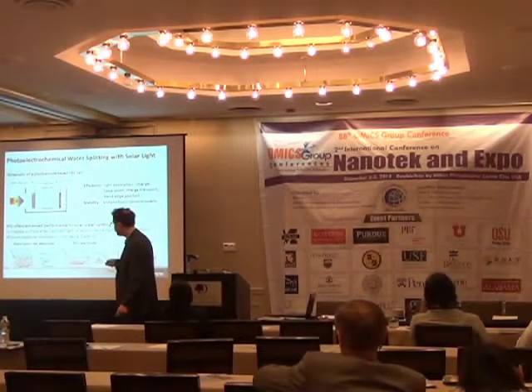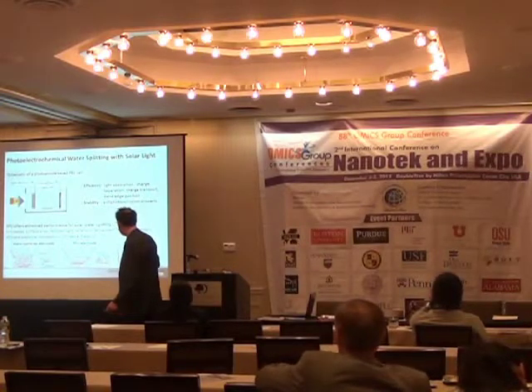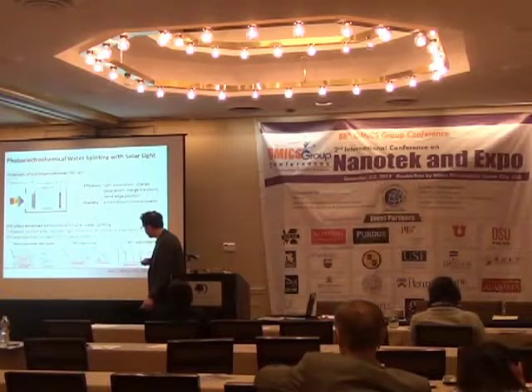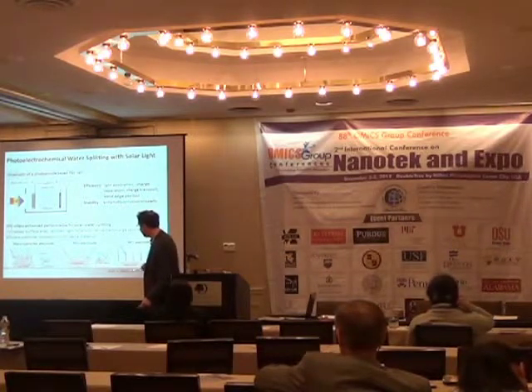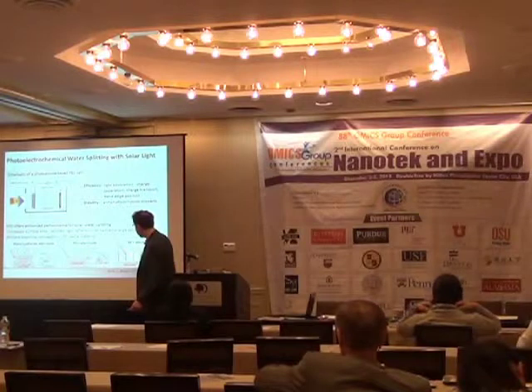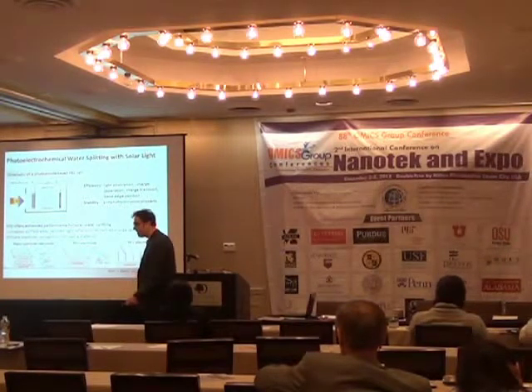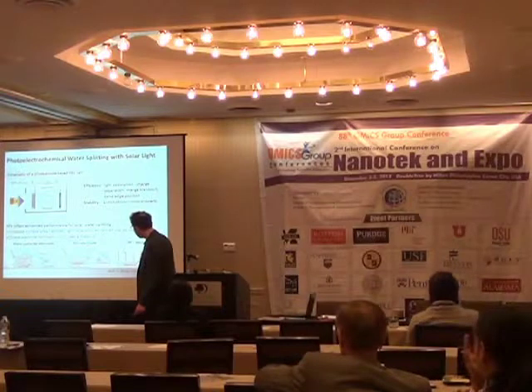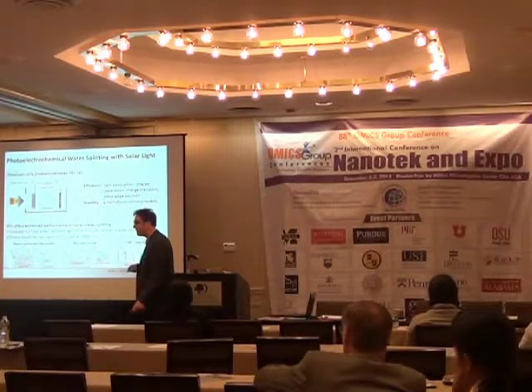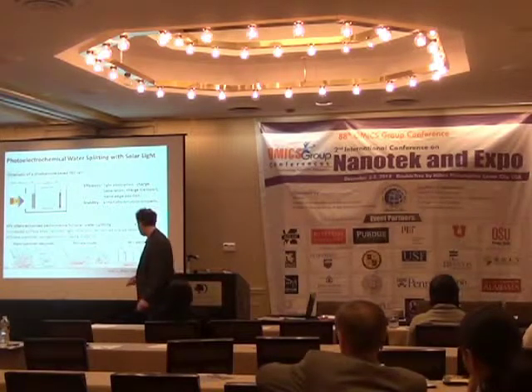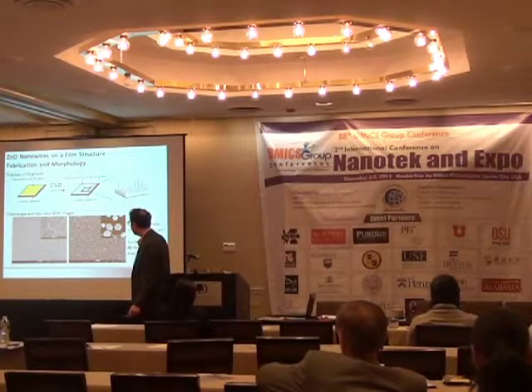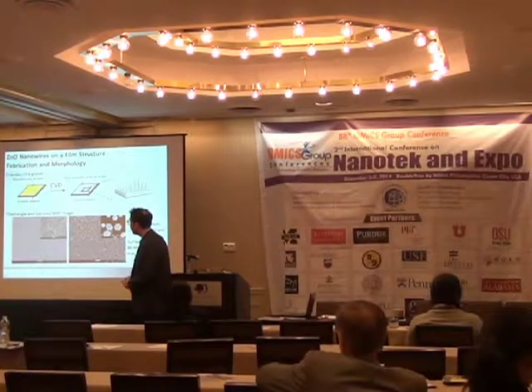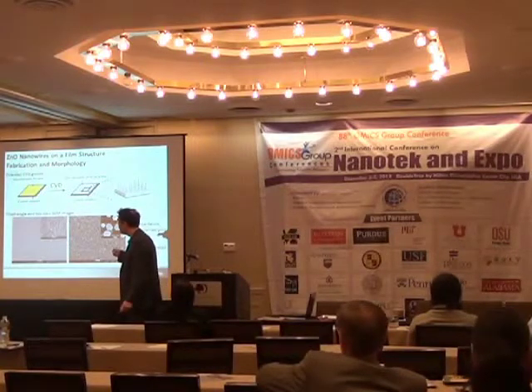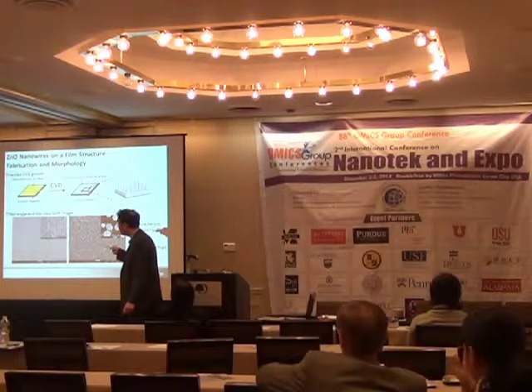So the idea is to combine both a nanoparticle and film electrode, and this is the type of design that you have, where you have the nanowires on top of a single crystal material here. So this part here is used to transport the electrons to the cathode, and the nanowires are used for the chemical reaction. The point of this design is that the nanowire on a film structure should at best be in the form of a single crystal, which is very difficult to fabricate. Okay, so we are trying to fabricate that with zinc oxide, and I show the result here. The process is very easy. It's a chemical vapor deposition that is controlled by again a gold catalyst on a sapphire substrate.